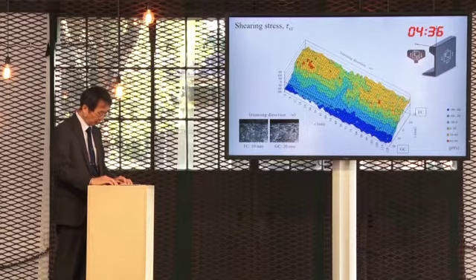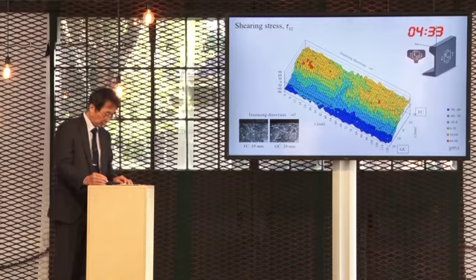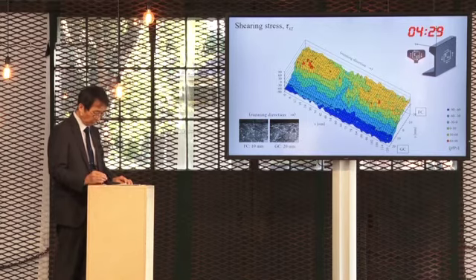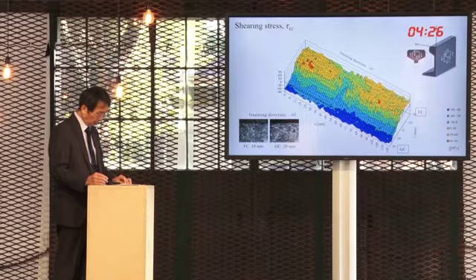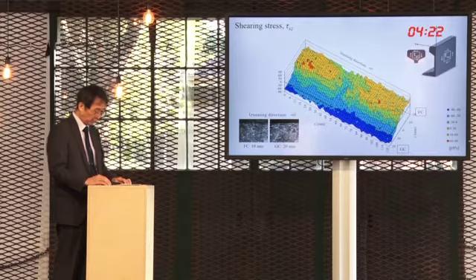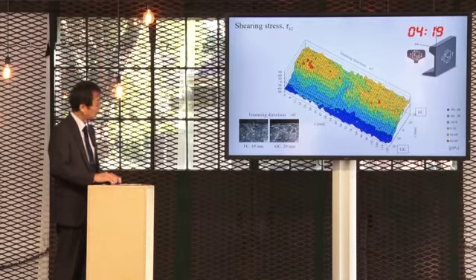The second feature is the difference in the stress between the gauge corner side and the field corner side. The stresses on the field corner side from the center line of the rail show positive values, whereas on the gauge corner side, they show negative values. It's known that the plastic flow of the surface layer of the rail has opposite direction between the gauge corner and the field corner side. The behavior of the shearing stress tau xz corresponds well to that of the plastic flow. In other words, we can detect the state of the plastic flow from the X-ray measurement.